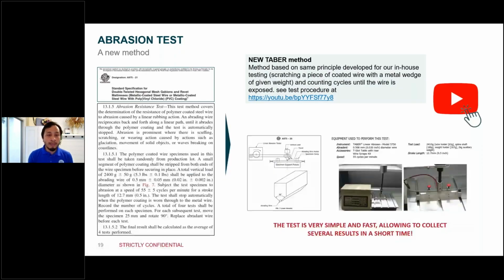Now, this one is a new standard, a new clause that has been added in ASTM A975 2021, and you can see from this clause, an abrasion resistance test has been added into the test index. This abrasion test compares the performance of advanced polymer coating, as opposed to the typical polymer coating that is normally used in Malaysia, which is PVC. All right, and you can see here, this coating will have a better resistance to abrasion. What the tests do here is they try to scratch the coating and measure how many cycles it takes before the base layer of the base wire starts to be exposed. And just for comparison's sake, you can see that with the advanced coating you will get about 450 cycles, as opposed to PVC, which is only about 50 cycles.